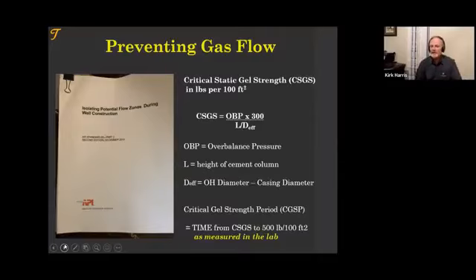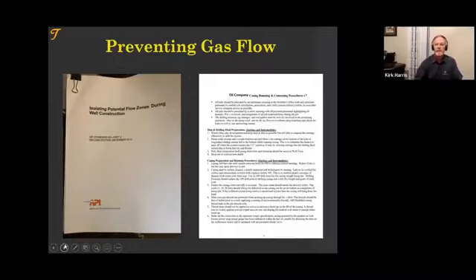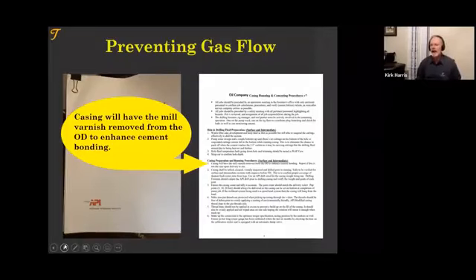The problem with this is that gel strength does not stop flow, in my opinion. It stops the percolation of certain size bubbles, but you need set cement to stop flow, not just gel strength. So when we're looking at what stops gas flow, make sure we write it from practice and put it into our local practices. Here's one local practice we have, very specific: the casing will have the mill varnish removed from the OD to enhance cement bonding. This is a different kind of gas flow. It's gas flow along casing cement.